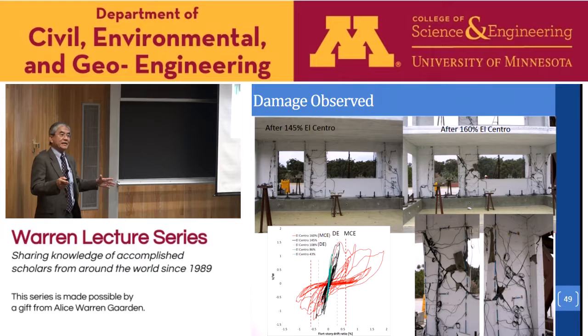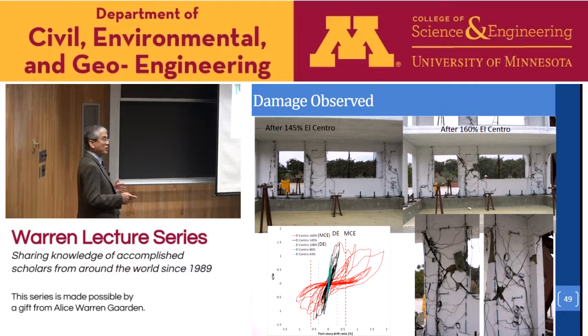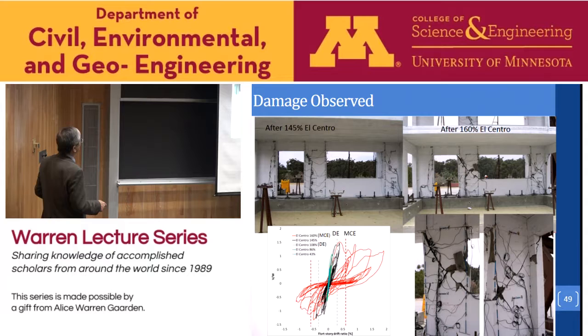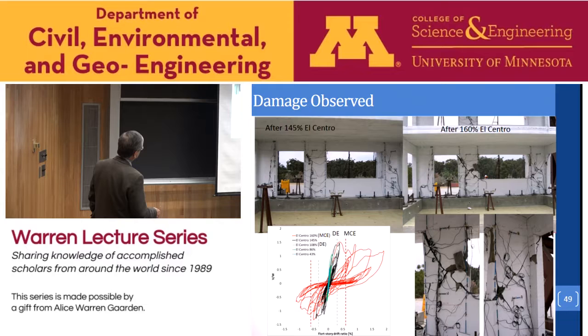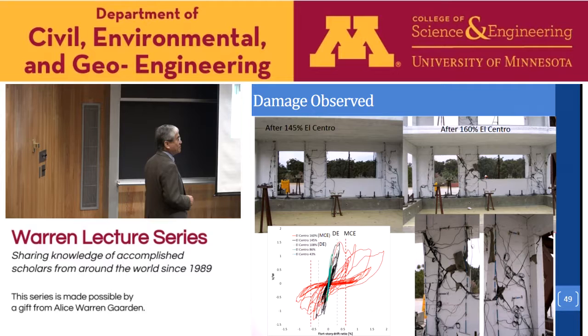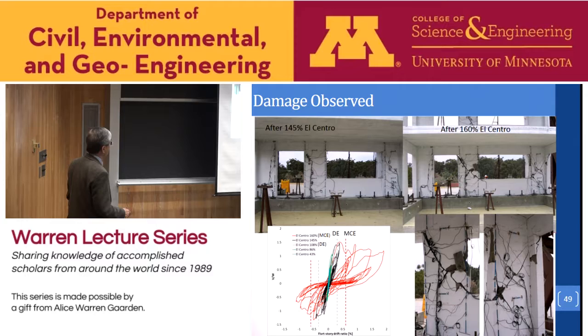And we did validate with our finite element model. We did a finite element study with an undamaged structure, and it seems to perform much better and meet this drift requirement. But in this case, the test structure, because of the prior damage, drifted in the very last run much more than what we imposed in design. But the amazing part is the ductility exhibited by this structure. The structure is really quite ductile, considering the brittle shear behavior developed in the piers.